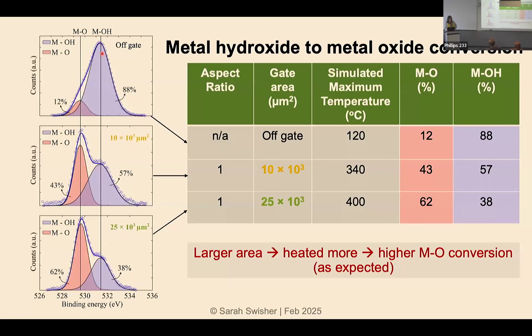This huge peak over here in the purple, that's our hydroxide peak. And so we've done very little to convert this into the oxide phase here, right? So this is as expected. And then as we go from this medium-sized device to a larger device, you can see that we have a higher conversion to metal oxide, which again, it's the larger area, so it's heated more and we get that better conversion, and it's all consistent with our simulations and our TFTs.